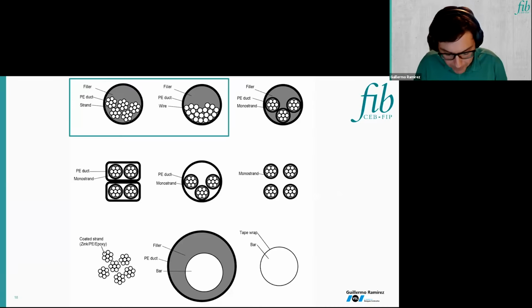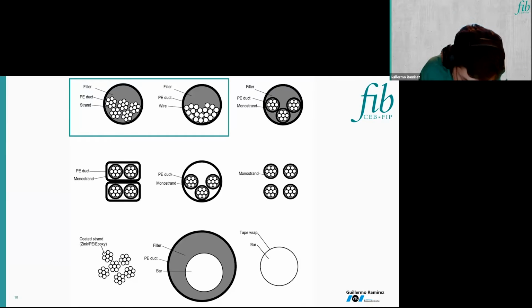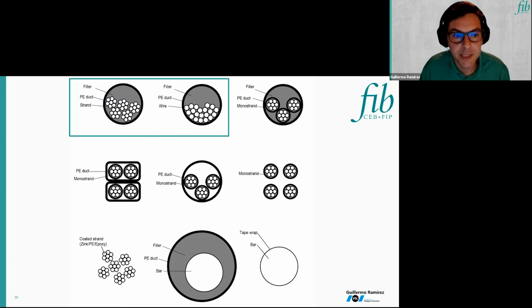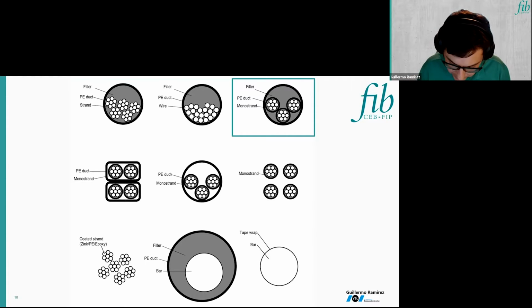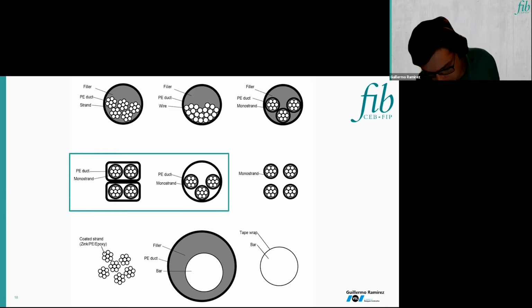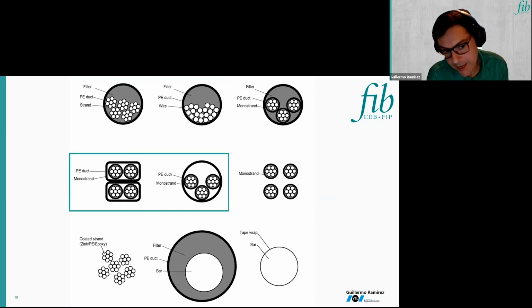As external tendons, we can find bare strands inside the global polyethylene duct with a filler, which can be either grout or soft fillers such as wax, grease, gels, and we can have the same configuration with wires instead of strand. Adding an additional layer of protection, there's the option of monostrands inside the global PE duct, all filled with cement grout. Still with strands, we can find some options, as just described, but without the cement grout. These have less layers of protection, and the outer ducts serve the purpose of helping during the installation. The option is found both with round pipes and rectangular pipes.